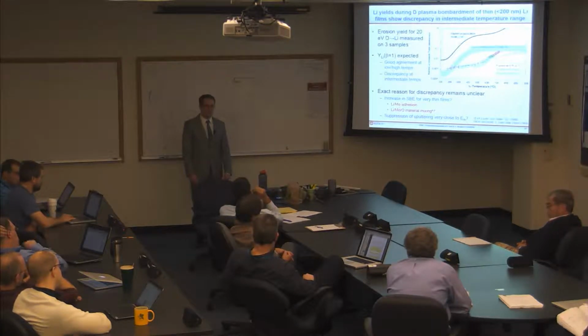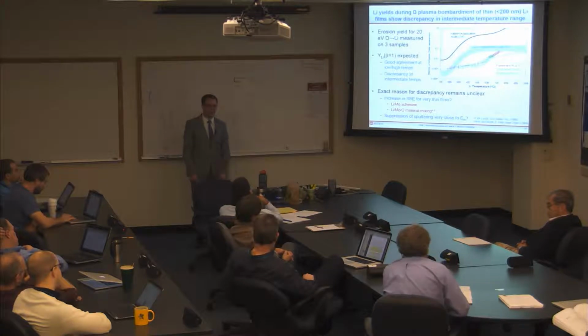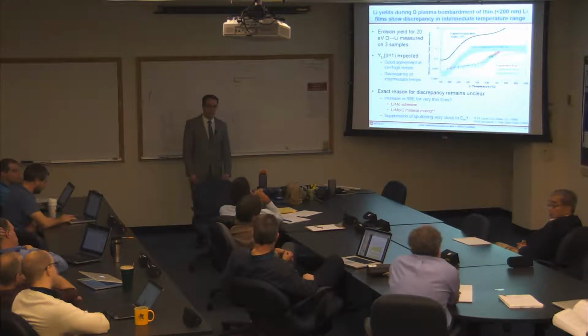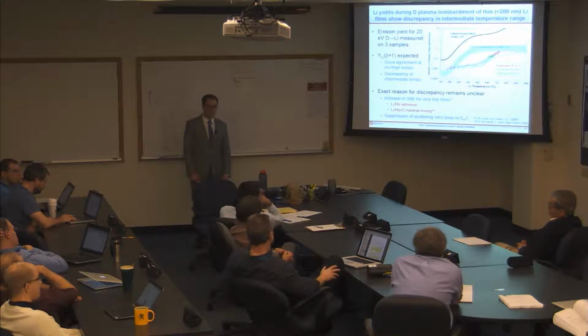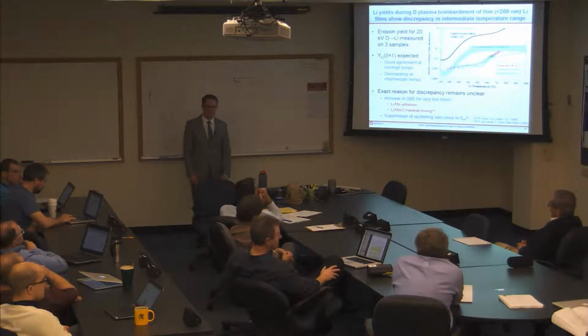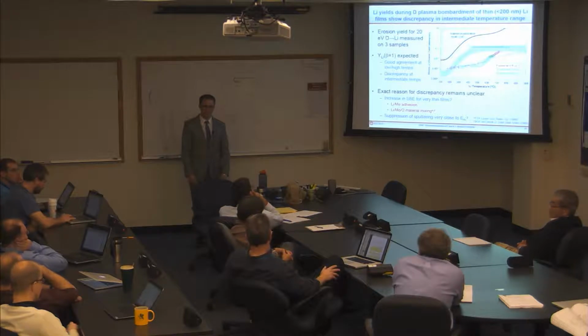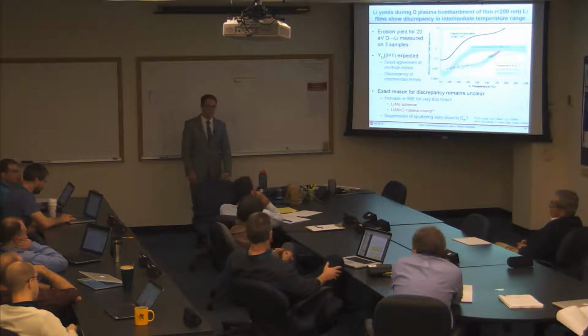And I couldn't find any papers where anyone ever measured greater than 1-to-1 hydrogen to lithium concentration. But you're in this dynamic situation where you're just feeding it heavily, and this very thin amount of lithium has been totally bombarded. Yeah, it would seem like this is a candidate for an MD simulation, not a measurement. Yeah, I agree. And maybe you want to do both.